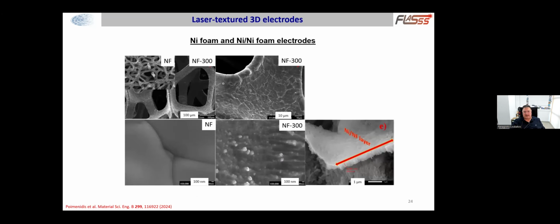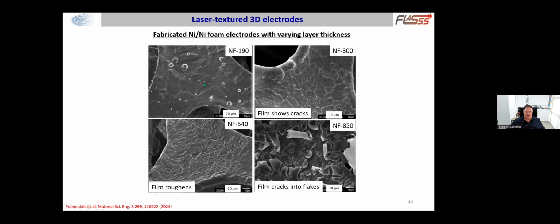This is how it typically looks when looking at the SEM micrographs. On the left column, we can see the pristine nickel foam in various magnifications. And on the right side, we can see in the same magnifications a film consisting of a lot of nanoparticles that are deposited on the surface of this nickel foam. In this case, it is a film which has a nominal thickness of 300 nanometers, and this is how it looks. We have a much increased roughness in the morphology of this foam. Typically, we develop films of various thicknesses, ranging from 200 nanometers up to 850 nanometers. In the case of the thickest films, the 850 nanometers thick, this is practically not a film anymore, but a mixture of cracks and flakes and so on.